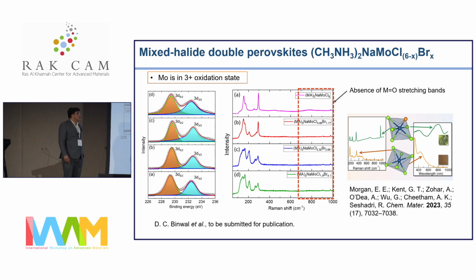And before that, it is important in molybdenum and any transition metal compound that the oxidation state is carefully analyzed, because the number of unpaired spins we talk about in a transition metal ion depends on oxidation state, and that might significantly impact the analysis of magnetic data. So here we see the molybdenum in this series of compounds, and the previous compounds too, is in 3+ state. We don't see any impurity of other oxidation states, and that becomes further clear from Raman spectra, where typically if there is an oxide, one would expect a peak around 800 inverse wave number, and also around 950 inverse wave number. We don't see those; very tiny peaks, of course, can arise from surface oxidation.